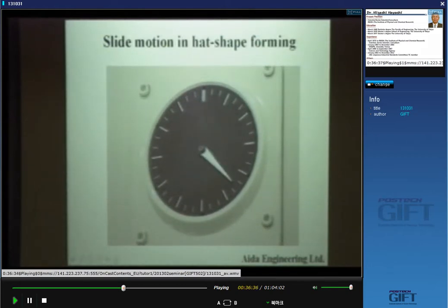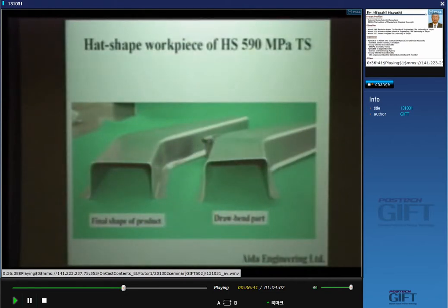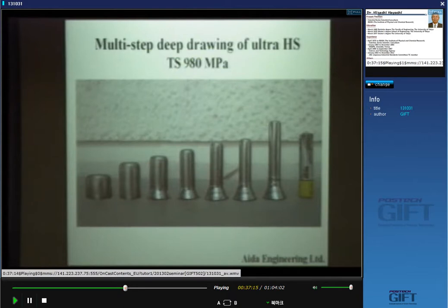So for the hat shape workpiece, the first step is the draw bend. In this case, some wall curl and springback, and also a twist happens in this direction. But finally, the final shape of the products is normal, in very good condition. And in the other case, they tried very high, ultra-high strength steel sheets, 980 megapascal materials, for small size batteries. In 7 steps, they can make very deep caps from these very high strength materials by servo-press.